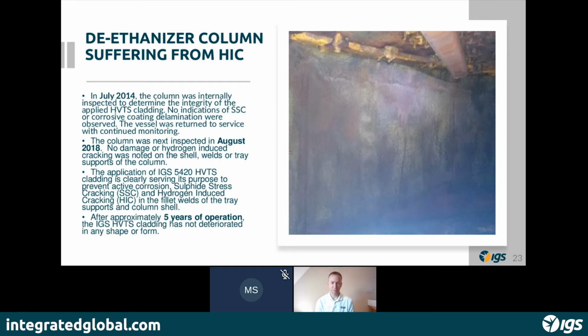And what I want this to demonstrate is that even if you have surface cracking, as long as that cracking isn't going beyond your corrosion allowance, as long as that cracking can be mechanically addressed and it's being driven by a corrosive process, so it's not mechanically driven, it's driven by corrosion, we can stop that. And we've many examples where we're applying this system in order to address localized cracking issues. For example, on weld seams or in areas where you have heat-affected zones.